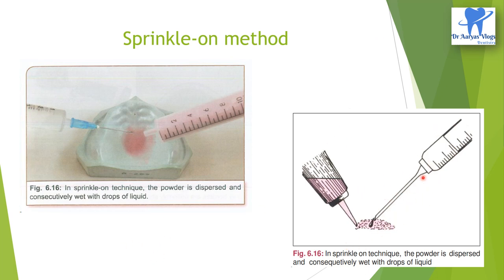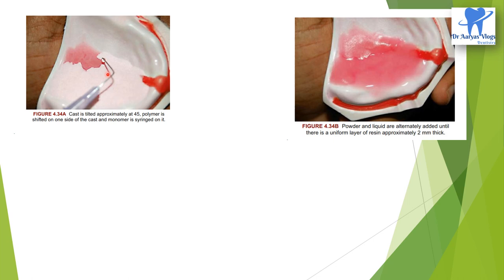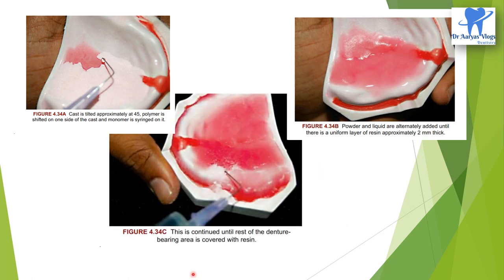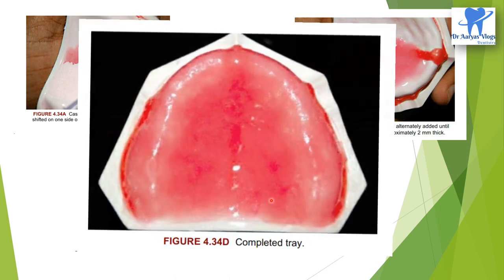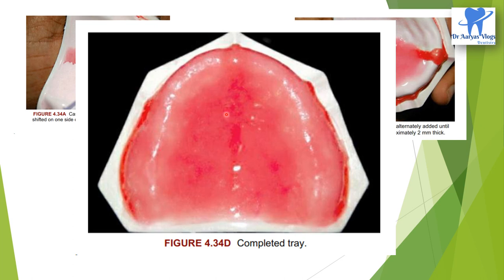Here, powder is dispensed and consecutively wet with drops of liquid. In this method, the cast is tilted approximately 45 degrees, polymer is shifted on one side of the cast and monomer is syringed on it. Powder and liquid are alternately added until there is a uniform layer of resin approximately 2 mm thick. This is continued until the rest of the denture bearing area is covered with the resin. And this is the completed self-cure tray.